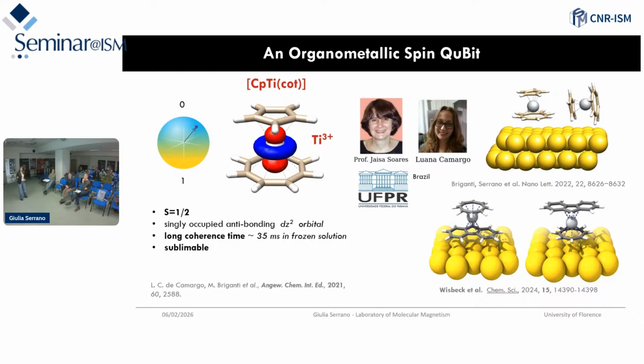No, so the coherence time tells us that the spin information, so the phase of this spin, which of course can move, is retained for 35 milliseconds. And this is a problem of any magnetic ion, also without the organic ligand around. Actually, if you have a magnetic ion on the surface, the problem is even higher because you have anyhow a crystal field that the ion senses because it is in a particular position on your surface. So also in that case, you have some asymmetry because you have a spin on the surface. Okay, but no. You don't have a ligand field effect on this molecule. We have it, but it's very small.